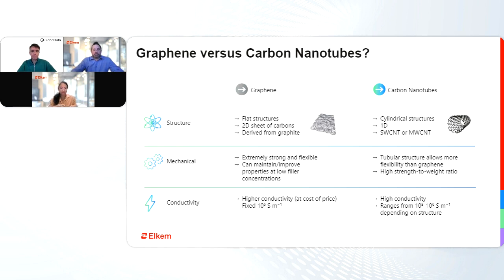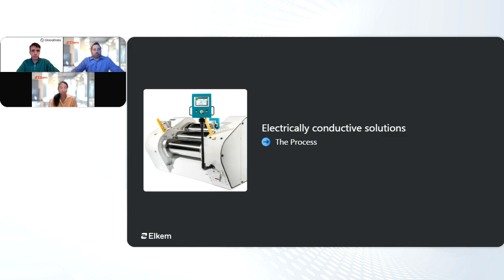Also, carbon nanotubes have high conductivity that ranges from 10 to the power of 5 to 10 to the power of 6, whereas graphene will be relatively fixed at 10 to the power of 6. Yes, graphene will have that higher conductivity, but there is a higher cost involved with that. So hence, this was a decision as to why we've moved forward in developing our product using multi-wall carbon nanotubes.